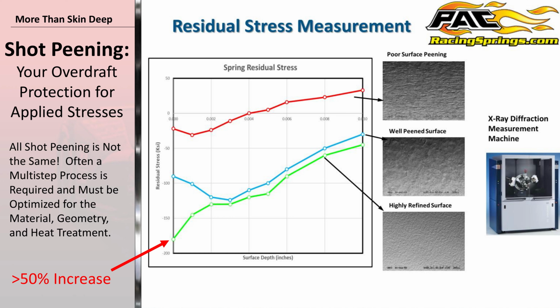And again, look, you can see that this stress is highest at the top. This is 2,000th of an inch. When you get down here 1/2000th, we're talking about 150 KSI. That's 150 KSI on something that's around 300 KSI. We've given ourselves another 50% stronger surface than we would have had without the peening. So it's amazing what that will do. But, that's really important